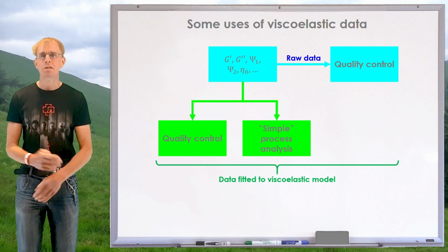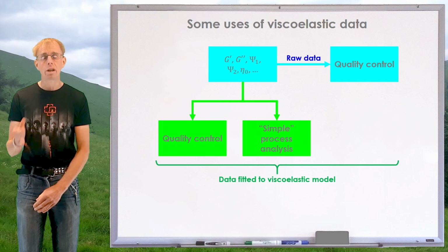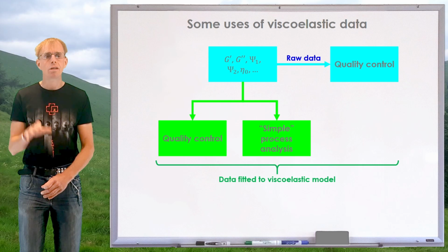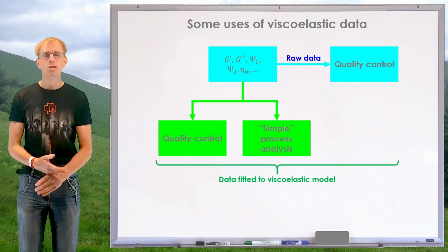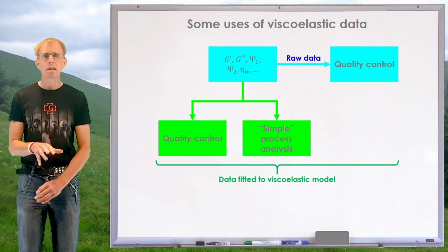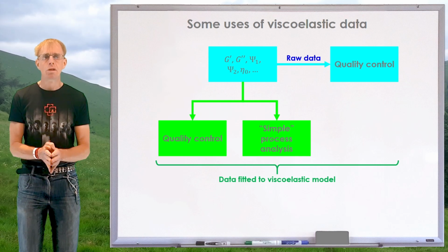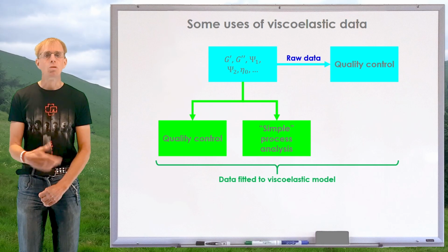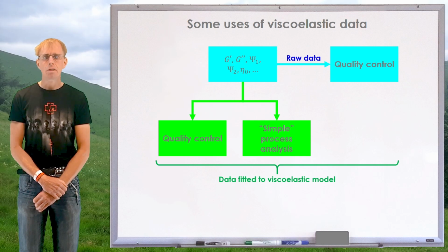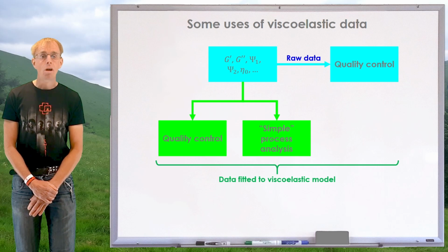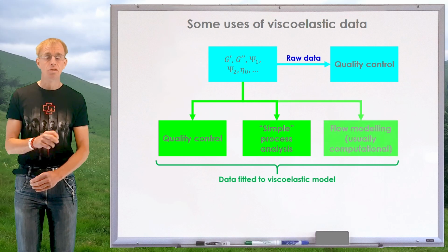And that might be pertinent, for example, when we're cooling an extrudate, and the stresses during that cooling process need to relax to a sufficient extent such that when the material we've extruded is solid, we don't end up with embedded stress in there that, over whatever service period the product is in, causes a lack of tolerance or problems. So we might be able to do some simple process analysis with parameters that we can back out from a simple viscoelastic model. We might take this yet one stage further still.